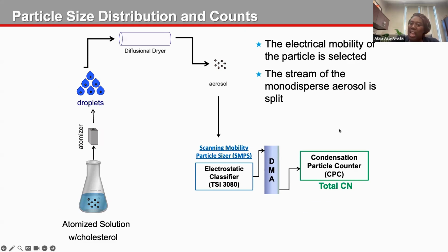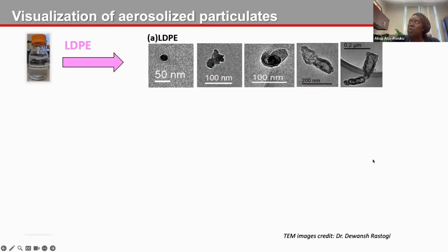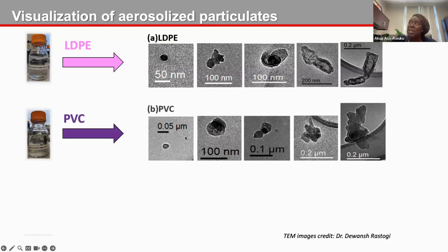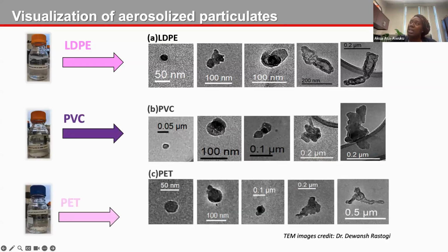In addition to this, we actually also did TEM deposition. We wanted to visualize the types of particles that were coming from the spray, what kind of aerosol we were generating from these plastics. And so our TEM results show that LDPE can create very spherical particles on the order of 50 nanometers or less. But as we increase the particle size, we get these agglomerates of LDPE particles that were leached into solution. We see something similar for PVC and also for PET.